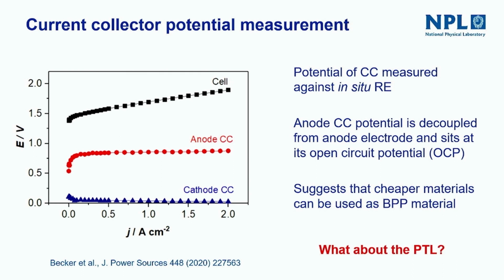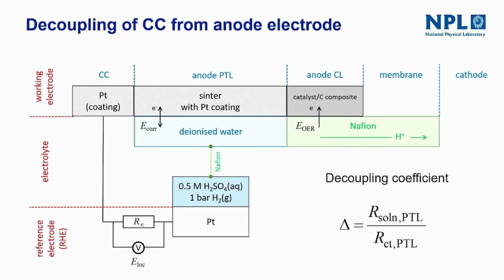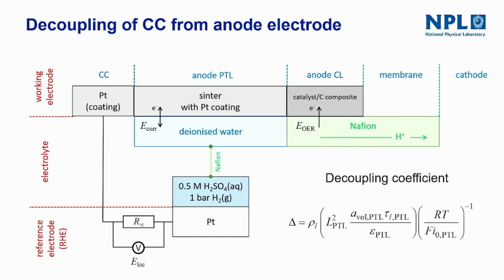That led us to ask, what about the porous transport layer? Because yes, we can replace all of the bipolar plates with something like carbon-coated stainless steel, which would be much cheaper. Can we also replace the porous transport layer? So I'm not going to go through the full details of the model, but essentially we came up with this decoupling coefficient, that basically the higher the solution resistance, the more decoupling there is, but it also depends on the electrochemical properties of the porous transport layer material, which in this case is platinum. So that's the equation for the decoupling coefficient.